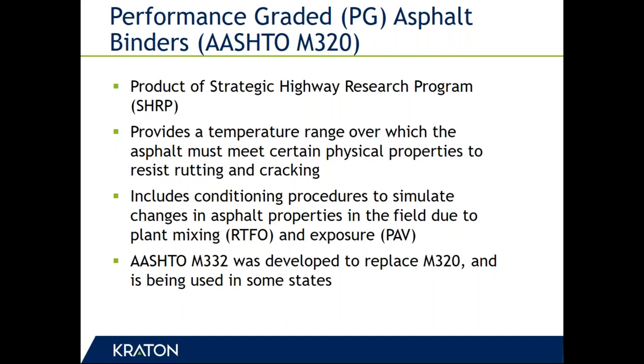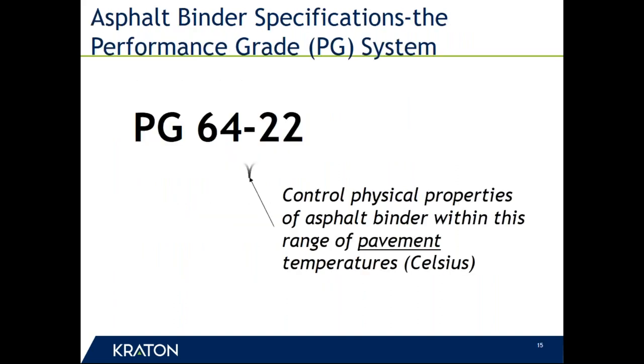Also, you have conditioning methods that replicate plant mixing, which is the rolling thin film oven test, and then the pressure aging vessel test, or PAV test, is to simulate exposure in the field for a number of years before doing the low temperature and the fatigue cracking tests.